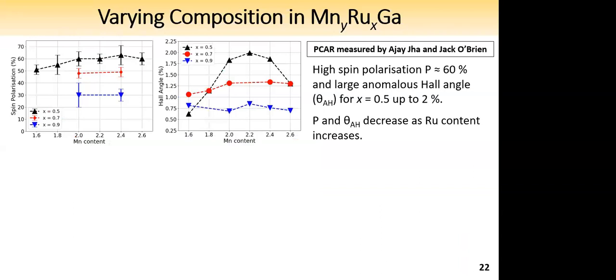Now looking at some spin polarization and Hall angle calculations. Both spin polarization and Hall angle show similar trends. Both decrease as a function of ruthenium, which indicates a shift of the Fermi level position upwards in the density of states out of the spin gap. We observe high Hall angles for the x equals 0.5 ruthenium series of up to 2%, which is about 20 times that of what we observe in iron.